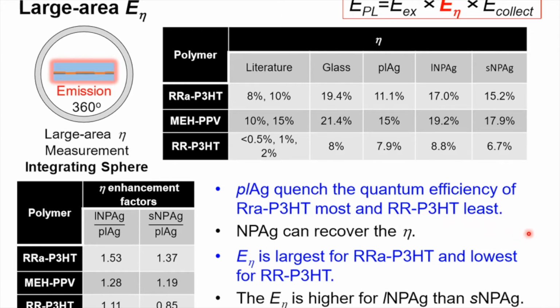The nanoporous silver does recover some of the quantum efficiency lost by placing the emitter on a metal. And the enhancement in the quantum efficiency is largest for regiorandom P3HT, the most amorphous polymer. It's also higher for the larger nanopore silver than the smaller nanopore silver.